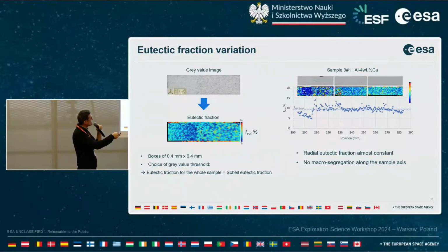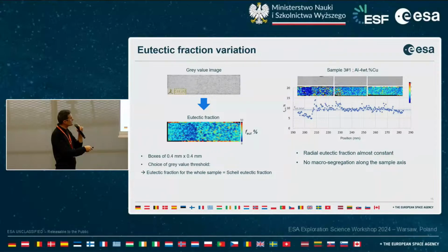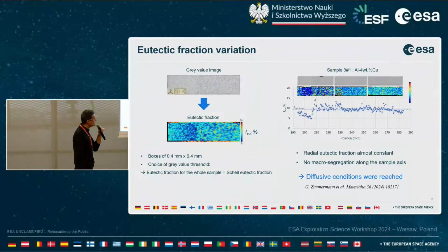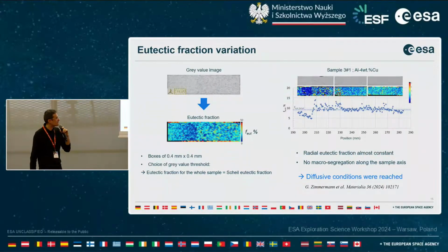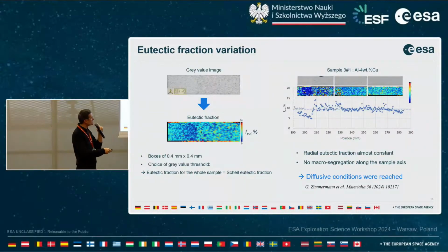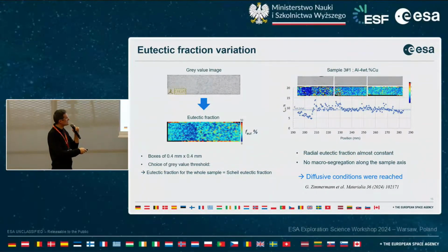And what was interesting for us is that the eutectic fraction is almost constant all along the sample, meaning that there was no macrosegregation along the sample axis, and that diffusive conditions were reached. And this is what we expect to obtain when we carry out experiments in microgravity. So all these experiments are summarized in a paper published by Zimmermann very recently. And obviously, since we show that the experiments have been carried out in diffusive conditions, they are a good candidate for comparisons with numerical simulations.